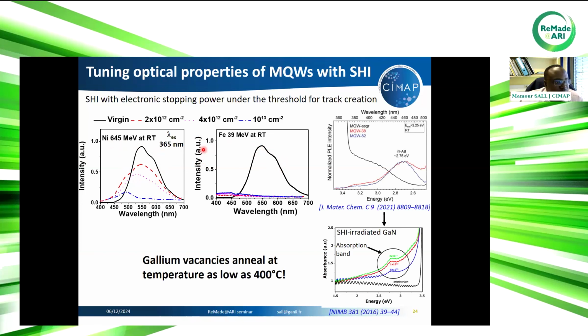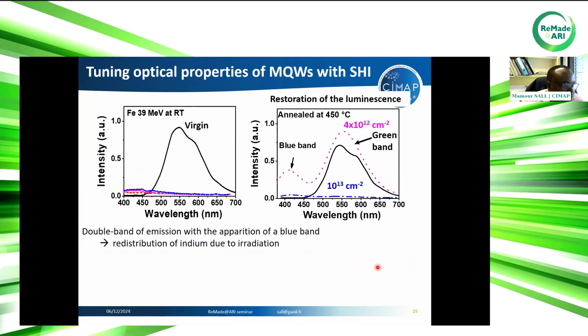From a previous experiment using excitation of photoluminescence, it was shown that this extinction of the photoluminescence in this multi-quantum well is in fact due to an absorbing defect at 2.8 electron volts in this material. This absorbing band is exactly the same as the one we found in gallium nitride irradiated by swift ions a few years ago. We know that this band is due to gallium vacancies, and gallium vacancies can be annealed at temperatures as low as 400 degrees. So what we have done is to anneal our multi-quantum wells after irradiation.